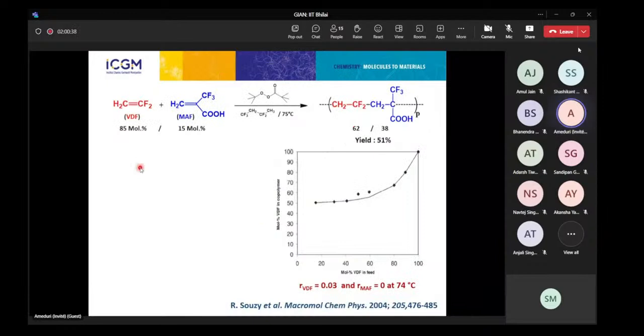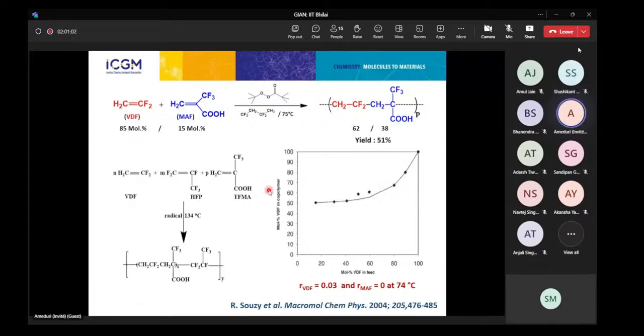Indeed, with VDF, the situation was very interesting, and my PhD student 25 years ago started some work on that and showed that we have a tendency to alternate. When you look at this diagram of composition, between, let's say, 20% and 75%, it's almost 50%. This is great. And it was even possible to make terpolymers, VDF, HFP, and MAF, in order to prepare this kind of Viton carboxylic acid compound. And the evidence of alternating copolymers was the low reactivity ratios. Usually when you make the product of the two reactivity ratios, you have to go to a tendency of 0. Of course, there is 0 here, but with such low reactivity ratios, we ensure that we have a trend to alternate.